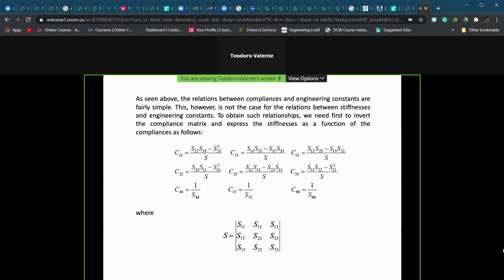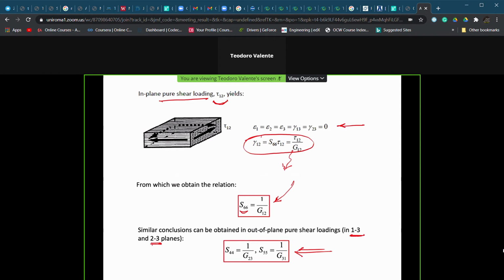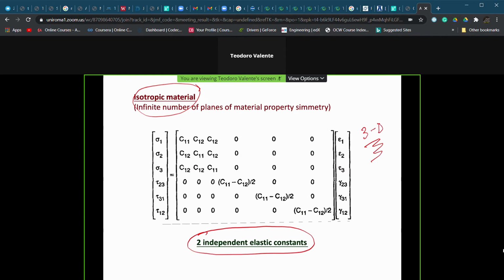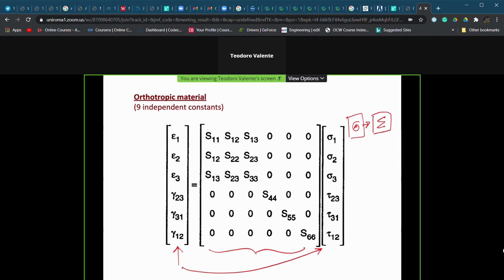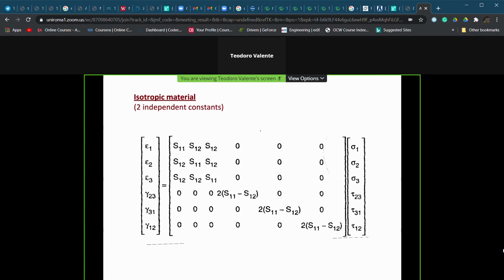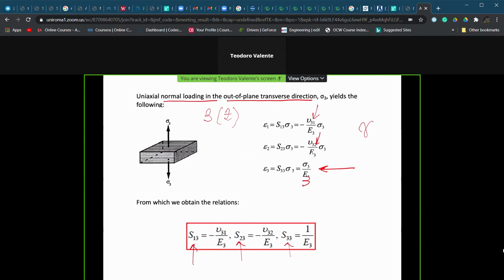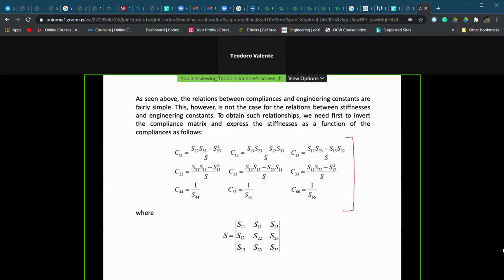These terms are also used if we want to write a relationship between stiffness and engineering constants, which led to this set of simple transformation equations, reported here. Remember, just to be clear, that the C constants are the ones with which we can calculate the stress knowing the strain, and instead the S constants inside the matrix allow us to calculate the strain knowing the stress.